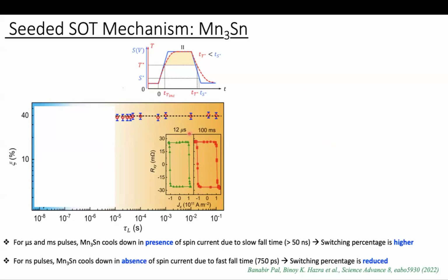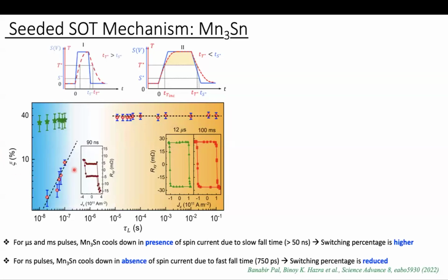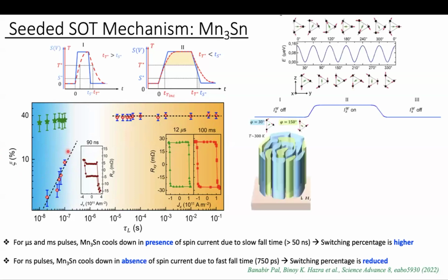When the pulse width is large, let's say millisecond or microsecond, we observe the switching percentage is large. It's almost constant, and it's 40%. And when we perform the switching at low pulse width, like a 100 nanosecond pulse, we observe the switching magnitude reduced drastically. Based on this, we propose the switching mechanism, which can be understood from this cartoon.